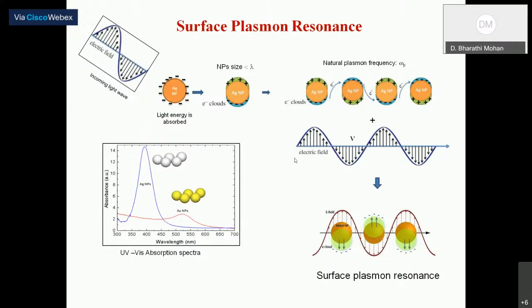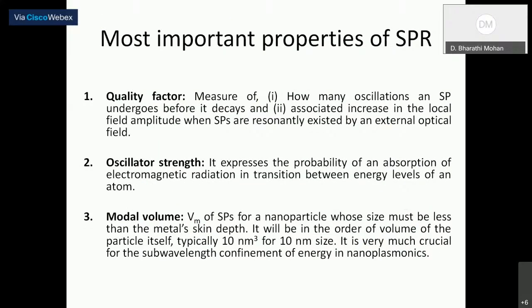This figure shows the UV-visible spectra of silver and gold nanoparticles. Silver nanoparticles exhibit a peak around 400 nanometers, whereas gold nanoparticles show a peak around 525 nanometers. So the surface plasmon resonance depends on the nature of the element, particle size and shape, and the dielectric medium. Before we choose any metal for making a SERS-based biosensor, we must understand the plasmonic properties of the metal.